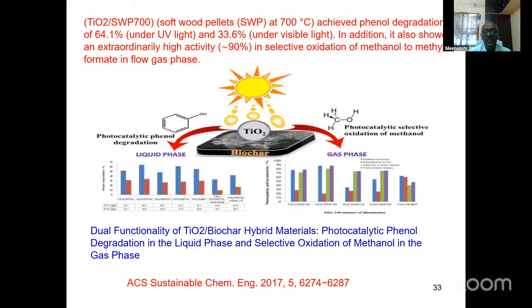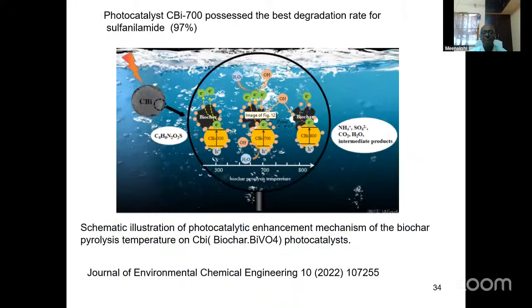Actually, normally when you take any alcohol, it is completely oxidized, but this is selective oxidation. So they found that this TiO2 biochar selectively oxidizes methanol into methyl formate, which is a very useful component in the industry. So there is selective oxidation of methanol in the gas phase and degradation of phenol in the liquid phase, the two functionalities of the TiO2 SWP 700 biochar.